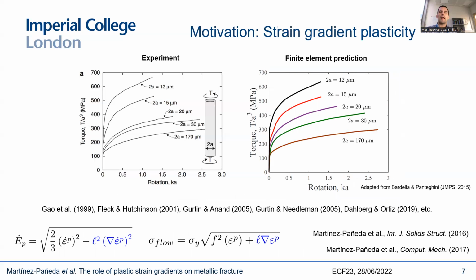However, the good news is that a number of very clever mechanicians have devoted their efforts to extend plasticity theory to small scales. And this goes back all the way to the pioneering work of Elias Aifantis, and then has been followed by many others, as you can see here in the slide. And the key point is that you build these strain gradient plasticity theories by typically defining your flow stress as a function of not only the plastic strains, but also the plastic strain gradients, or defining the plastic work, again, not only as a function of the plastic strains, but also of the plastic strain gradients. And of course, the moment you bring a gradient of deformation into the picture, then you need a length scale due to dimensional consistency.